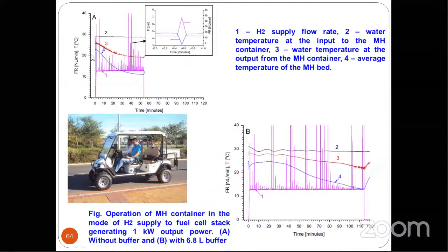Then if you see the temperature of this tank, because of the low thermal conductivity of the metal hydrides, it is unable to supply heat fast at the required rate to generate hydrogen. So it will release the hydrogen, but it takes heat from itself, means the sensible heat, to release the hydrogen. Because of that, the temperature decreases inside the cylinder. Once the temperature decreases, the pressure also decreases as per the PCT curve I have shown previously.